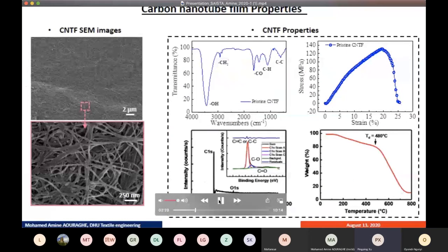As produced, the carbon nanotube film by floating catalyst vapor deposition method is a condensed entanglement of carbon fiber as shown in the SEM picture. The material is mainly fabricated with carbon atoms, as shown from the FTIR and XPS results. In addition, the carbon nanotube film has good mechanical properties with a tensile strength of around 140 megapascals and a strain of around 20%. Also, the carbon nanotube film can stand high temperature till 480 degrees before total degradation in air, as shown from the TGA curve.